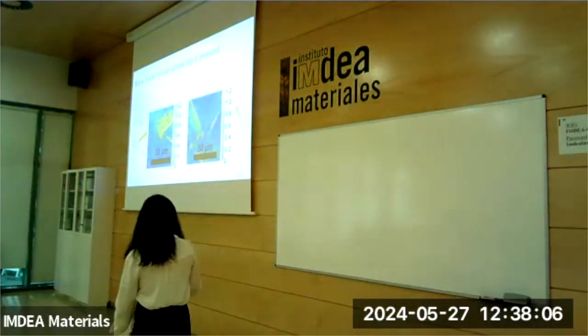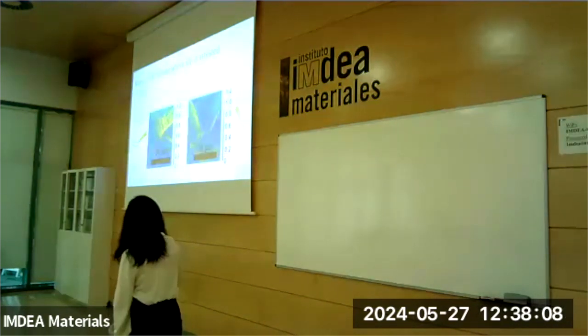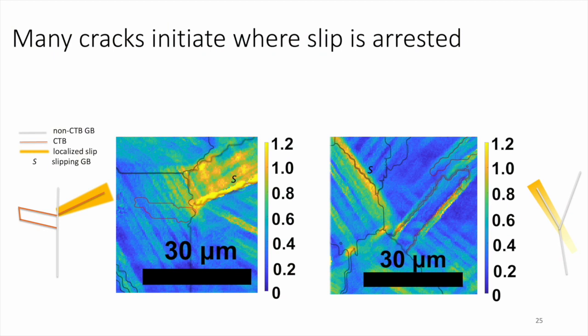We took two cases. In the first case, we have this crack initiated in this area where we have this slipping boundary, and the slipping boundary is facing a very thin twin. The slip stopped here.